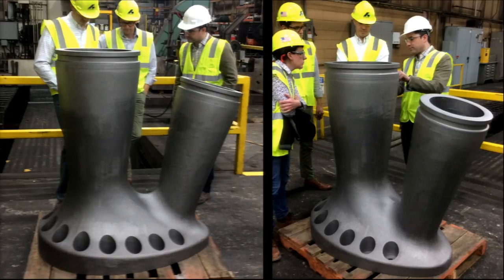Again, you can see that reveal that was machined in, which is another thing that we do and consider. We consider what features are going to be as cast features versus others that will be machined. So we could have cast those pockets. We could have made those as cast features, but had we done that, the edges of those pockets would have had to have very generous radii so that we wouldn't lose them in the casting process. But because they were a critical part of the aesthetics, we wanted those to have sharp corners. So we opted to machine all of those counterbores that you see in the base, and it creates a very clean-looking aesthetic. And these are the kind of design decisions that we are making to ensure that the finished product not only is constructible and manufacturable, but actually meets the architectural intent.